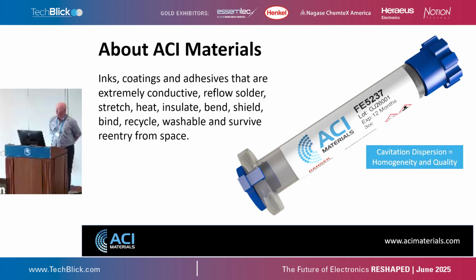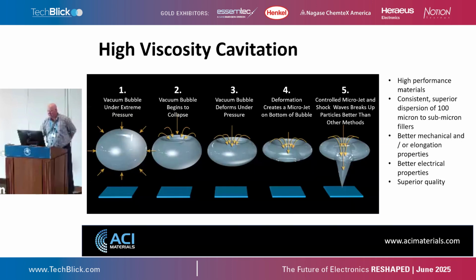And the key to ACI's manufacturing is in their cavitation, high viscosity cavitation dispersion. I've been in the coatings and inks business for a long time, and there are a lot of very traditional ways to manufacture coatings, three-roll milling, bead milling, etc. This is really a new way to disperse metallic and even pigments, carbon nanotubes, graphene very, very efficiently and evenly.